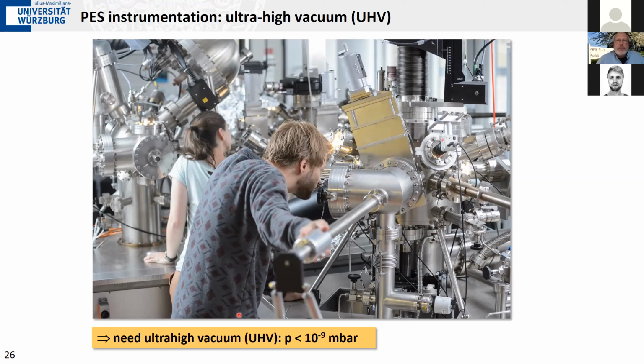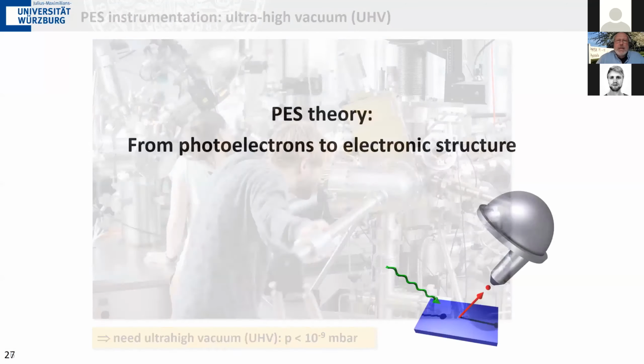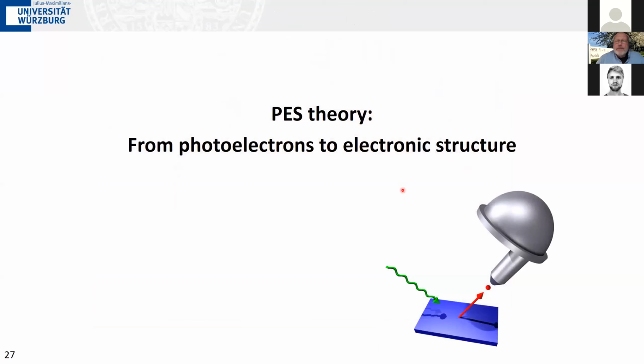You have to prepare your sample under these conditions, and if you prepare it in, for example, an MBE or pulsed laser deposition setup, you have to move your sample to the actual photoelectron spectrometer under ultra-high vacuum, which you can do, for example, with such magnetic transfer rods, but everything has to be done under UHV, and that makes the technique so expensive and difficult to handle. Okay, so that's instrumentation. That's all the dirty work that, at least the theorists among you, never see, but that's what takes most of our time and resources.